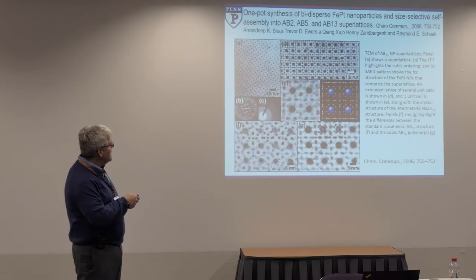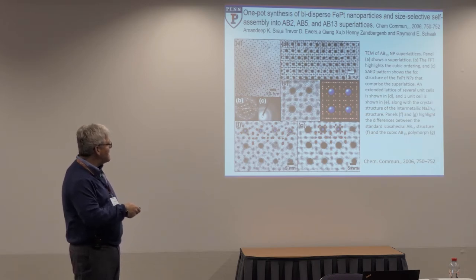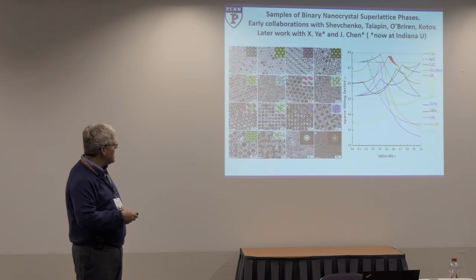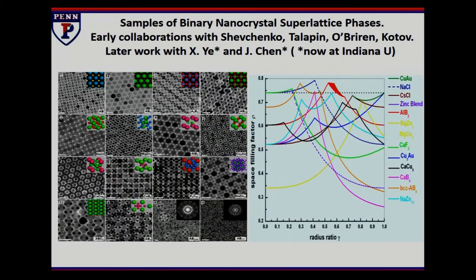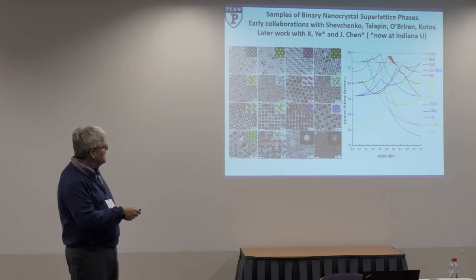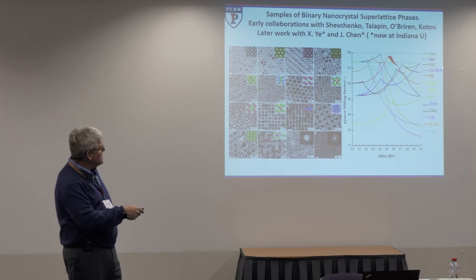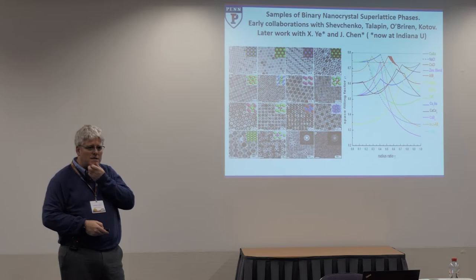So even the keys there, though, are the relative size ratio. Choice of the ligands on the surface is also valuable. But most of this is driven by the efficient packing of these constituents, so that the packing density of the materials. Actually, let me go back one. So this is packing density as a function of the radius ratio between the small and large particles. So all the range in here is right around where you get FCC and HCP packing, just above 70%, so around 74%, and BCC packing down in this territory. But any of the systems that get close to that in density to this 0.7 ratio have a fighting chance to be stable under the conditions of the design.